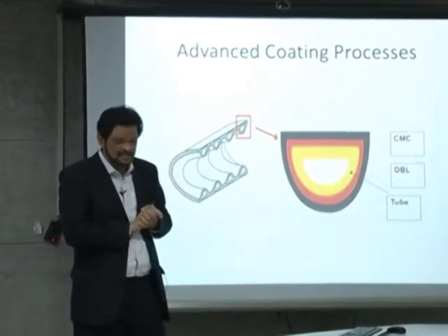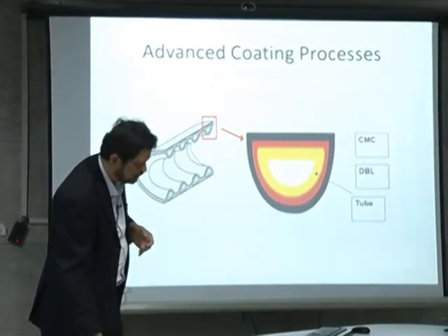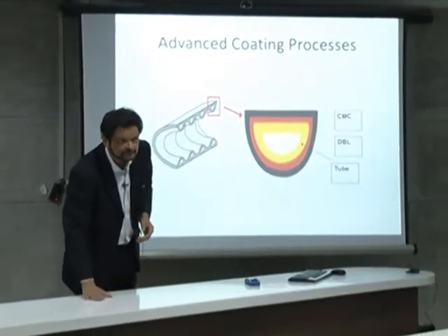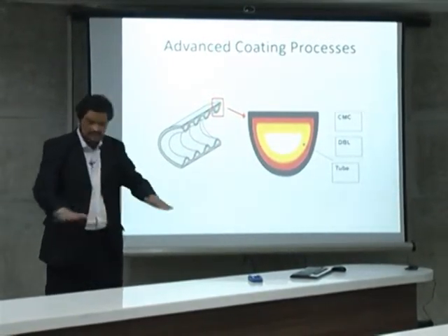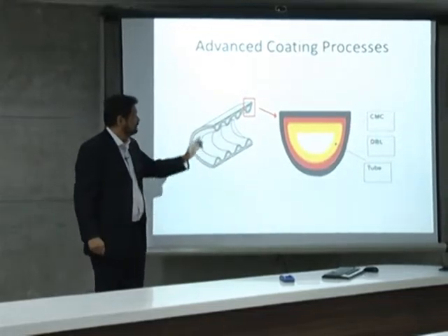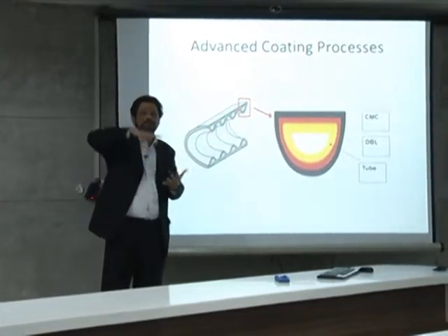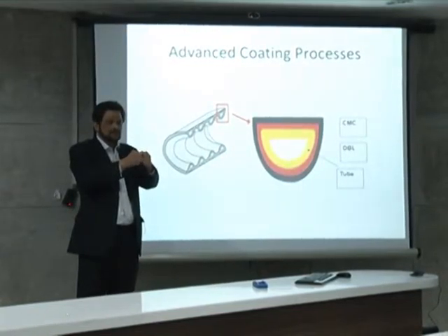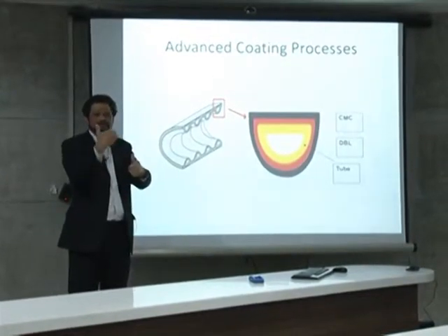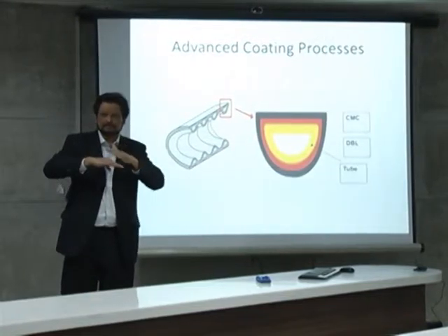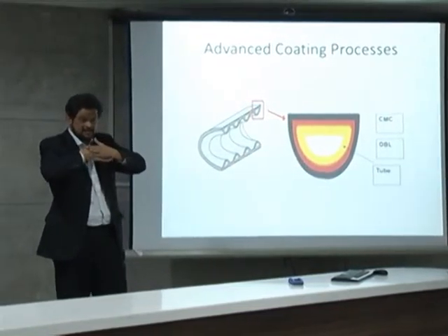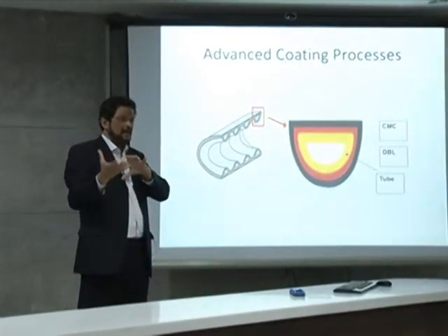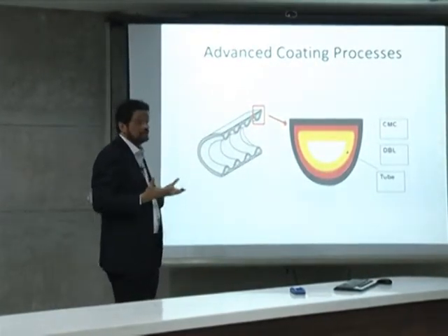The problem with coating is that if you look at the coating, this one probably has some kind of laminate on the top, right? This table, it's a coating. But when you look at this type of application where the temperature goes up and down, you can imagine it will change shape slightly and the coating will flake out. It will get released because of the stresses when it expands and contracts. So how do you take care of that problem?